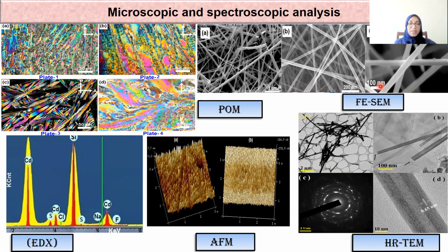Microscopic and spectroscopic analysis. FESEM, that is the field emission scanning electron microscopy, helped us to determine the morphology and particle size of CdS nanowire. These images show that the CdS nanowires are of uniform thickness and high aspect ratio and are well crystallized. CdS nanowires have very low diameter in the order of 7 to 10 nanometer and length in the micrometer range of 1 micrometer to 80 micrometer.